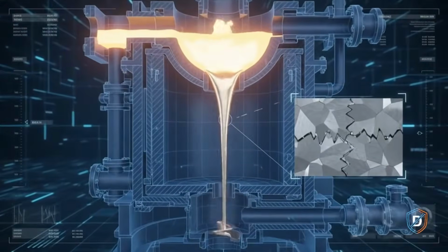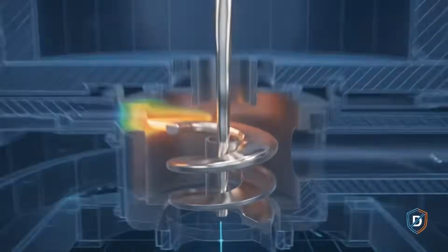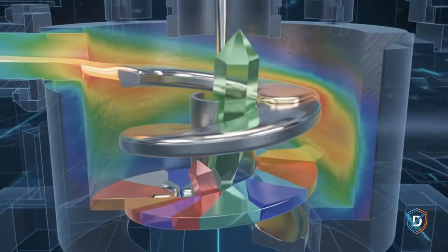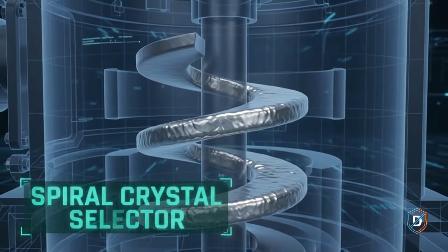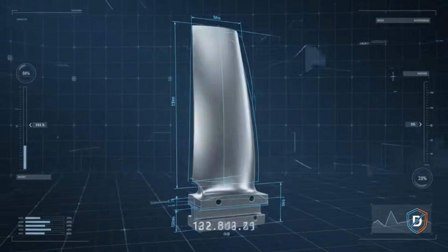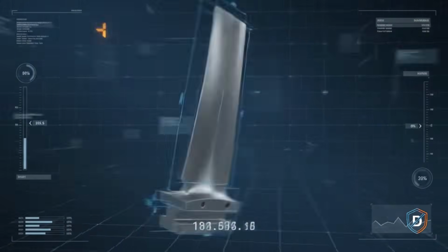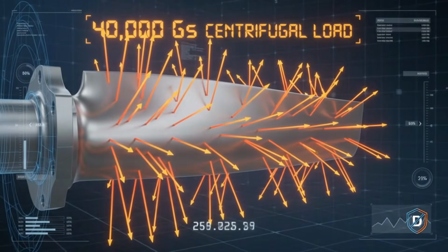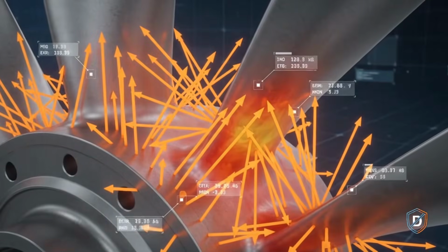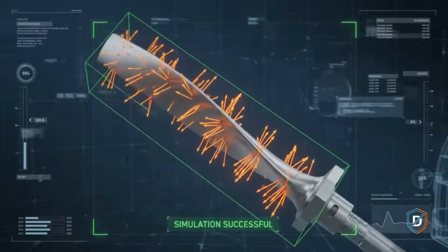In normal metal, microscopic borders between crystals pull apart under stress. To fix this, molten nickel is drawn through a spiral corkscrew mold that kills all crystals except one. Without grain boundaries, a single blade can hold 40,000 Gs of centrifugal force, the equivalent weight of 2 double-decker buses hanging from a piece of metal the size of your phone.